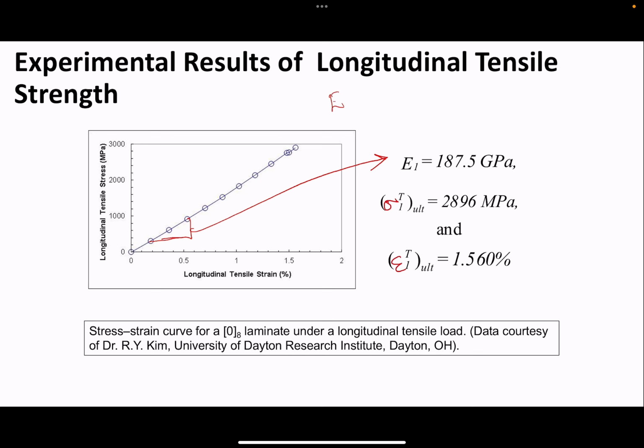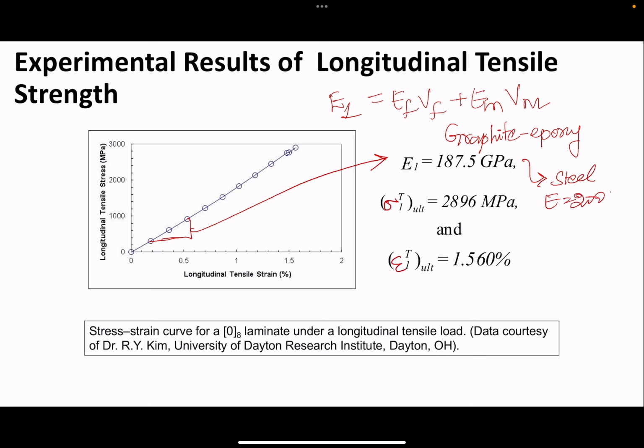And last week in class we learned the rule of mixtures. E1 equals EFVF plus EMVM, where the V's are the volume fractions and the E's are the Young's modulus of the fiber and matrix. So from this graph, we also get the value of ultimate tensile strength and ultimate tensile failure strain also. When does a specimen fail? 1.56%. These values are for graphite, epoxy, unidirectional lamina. You can see actually the E value is pretty close to that of steel, for whom the value is 200 gigapascals. But you get a lot of weight savings, and that's what makes us do this very complicated job of manufacturing composites.